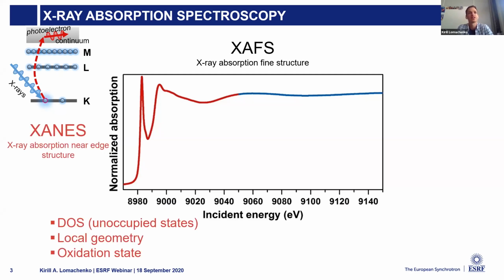So one part, the region closer to the X-ray absorption edge, is called X-ray absorption near edge structure, which is basically a reflection of the density of unoccupied states localized at a particular atomic species defined by the edge that we choose. It contains information about local geometry and the oxidation state of this species.